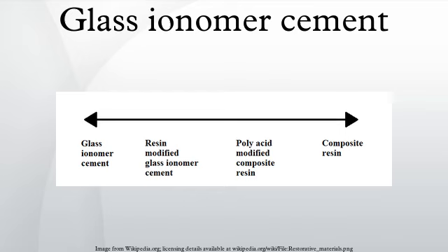Fluoride uptake in hard tooth tissue. In contrast to the fluoride absorption into dental plaque, fluoride absorption from GIC into adjacent enamel has been observed to be only twice as high as that from fluoride-containing resin composite in situ. However, in situ measurements of enamel blocks restored with either material show that after 28 days, enamel adjacent to GIC contained more fluoride than enamel adjacent to composite contained.